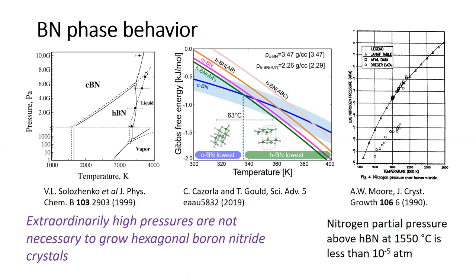The next thing to note is the wide range of where hexagonal boron nitride is stable, even though the diamond form of boron nitride is actually stable. A prediction made this summer says that at room temperature, cubic boron nitride is a stable form. But really, for kinetics to happen, for any sort of diffusion or reactions, you need to be operating probably above 1,000 Kelvin. Also, if you look at the partial pressure of nitrogen over hexagonal boron nitride, it's really quite low. At the temperatures we use, it's like 10 millionths of an atmosphere. So very low pressures are required for the boron nitride to be stable. So you really don't need the extraordinarily high pressures to grow high quality hexagonal boron nitride.